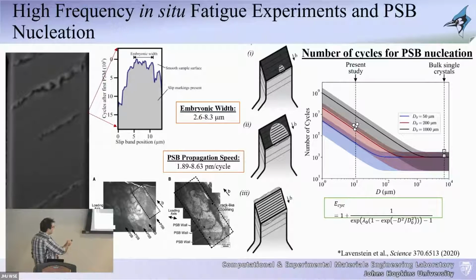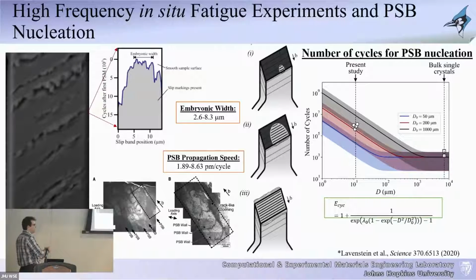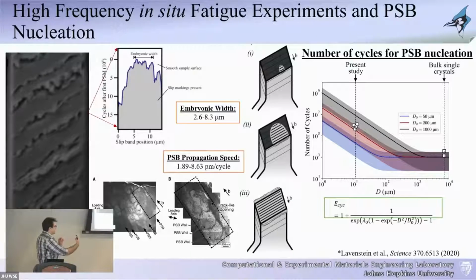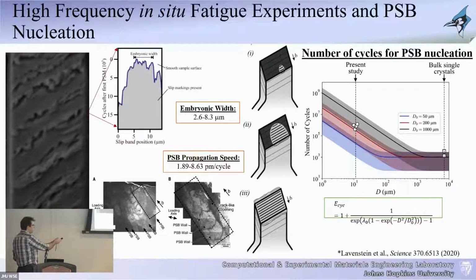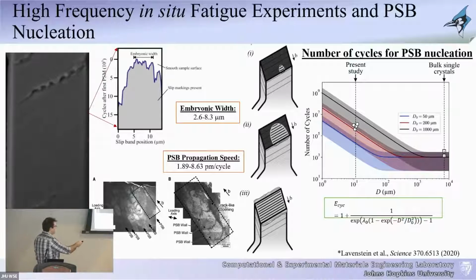And given that it is only 2 microns, or the minimum size that we've been able to observe is 2 microns, that basically indicates that they always nucleate internally. They don't nucleate on the surface. We never see something that is much smaller than 2 microns and propagating. So that basically indicates that they have nucleated internally, propagated to the surface, and then they continue to evolve until they span the entire cross-section of the sample.